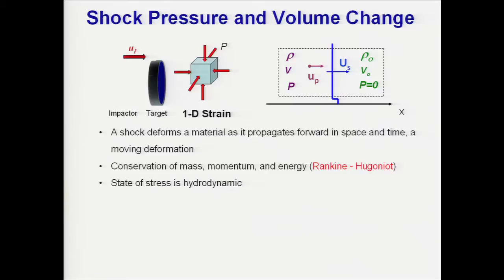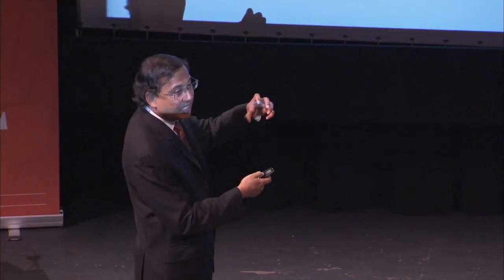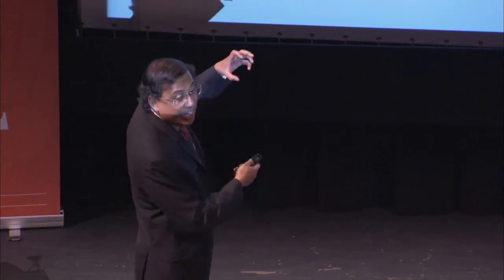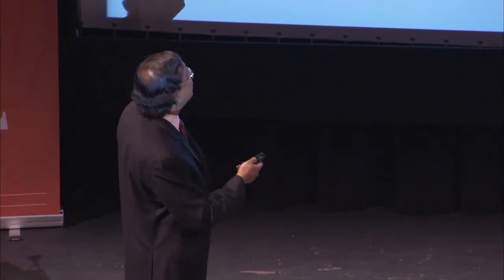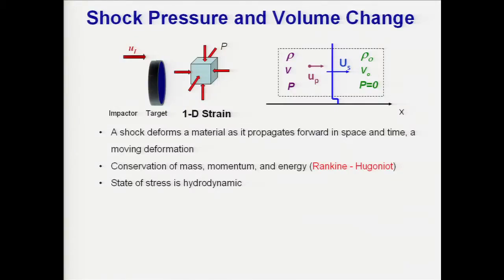There is the initial density. So behind the shock, the density changes because the size of the solid, which I showed you, the big cube, has become a small cube. So the density has increased. And correspondingly, the specific volume has changed. In order for us to have this very high density, we need high pressure. And so there is a pressure jump across this. And these jumps can be calculated using the conservation of mass, momentum, and energy, the so-called Rankine-Hugoniot relations. And the state of stress is hydrodynamic.